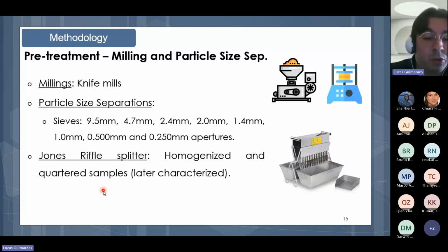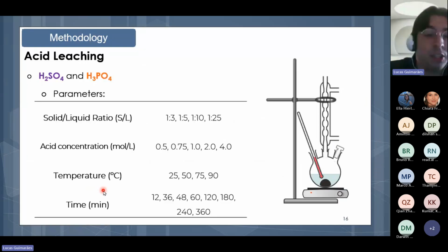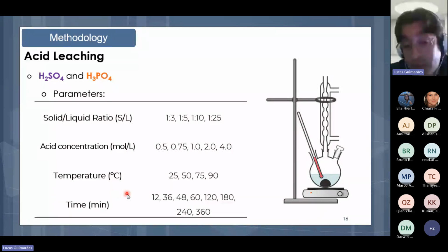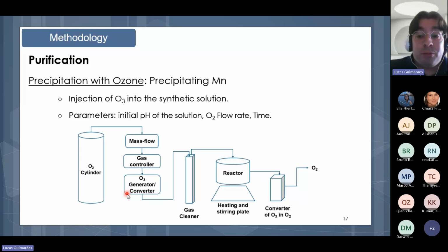And those samples were used in the next step, which was leaching, acid leaching with sulfuric acid and phosphoric acid. And the parameters studied were solid-liquid ratio, acid concentration, temperature, and time of the reaction. For the purification techniques, first starting with precipitation with ozone, in which the objective was to precipitate manganese. I injected ozone into the synthetic solution, which presented the same composition as the original solution with the best condition of leaching in the previous step. And the parameters studied were initial pH of the solution, oxygen flow rates, and reaction time.